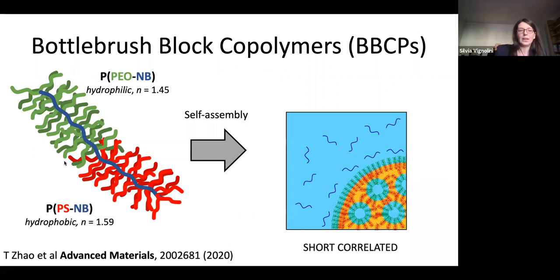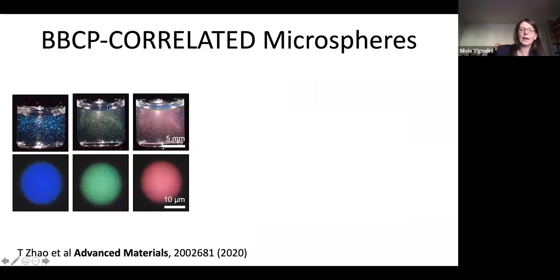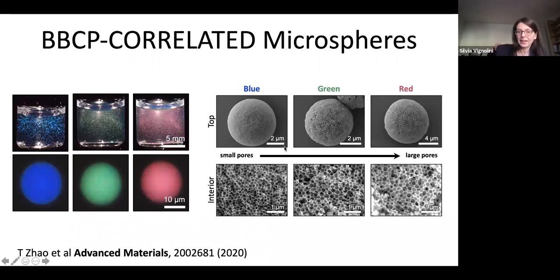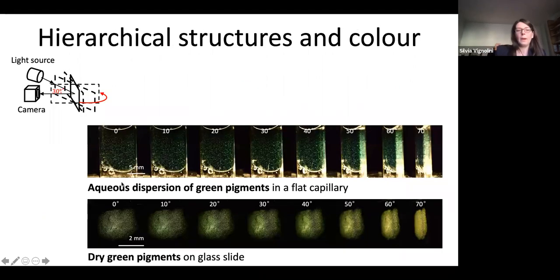But if you slightly change the chemistry and adjust the blocks, you can create what we call a correlated structure, where the system is slightly different. Now you don't have layers anymore, but you have a semi-periodic, actually correlated, system of holes inside the structure. And this one can give rise to a much more angular-independent color. When you look at them, for example, at different angles of illumination, over a really wide range, again you can get colors that are fully angular independent.